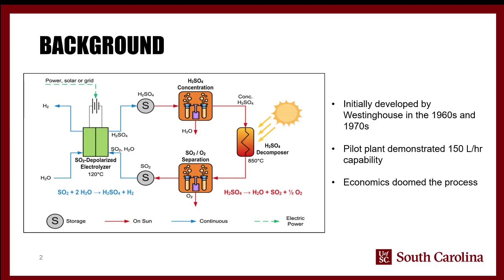So, at each part of the step, you extract the hydrogen and the oxygen, and you cycle this sulfur dioxide, a little bit of water, and the sulfuric acid. And the nice thing here is, once you get it started, the only real input is a little bit of water. Otherwise, you're just running this cycle continuously, generating hydrogen and oxygen pretty much as long as you want. So the pilot plant actually did pretty well. It demonstrated a 150 liter per hour capability, which, if you're at all familiar with initial technologies, to be able to scale it up to a pilot plant and actually have it work well is pretty incredible.